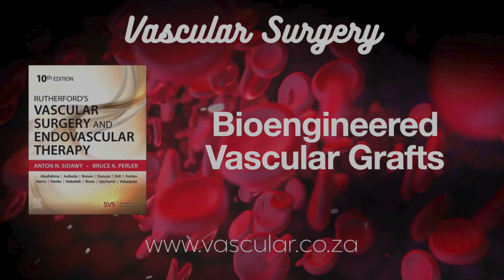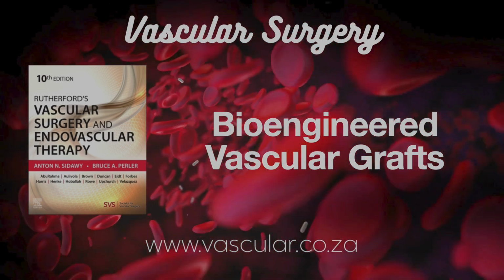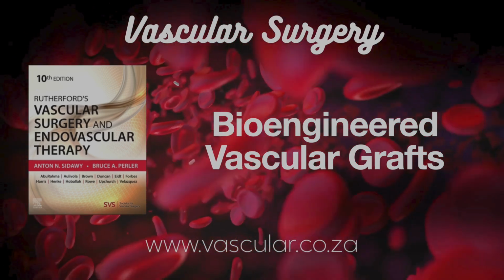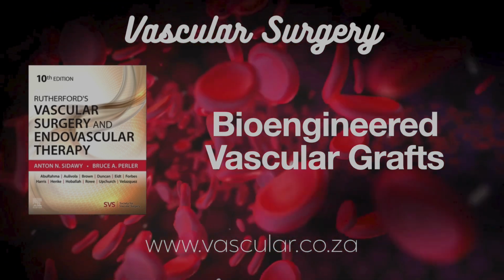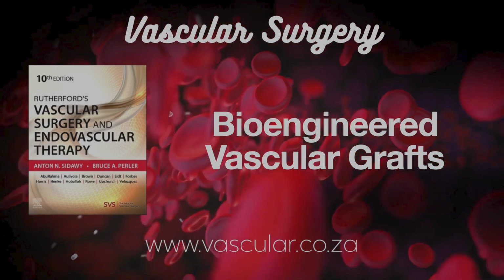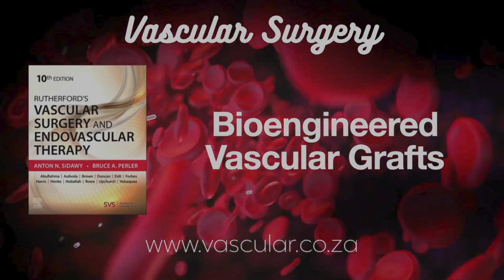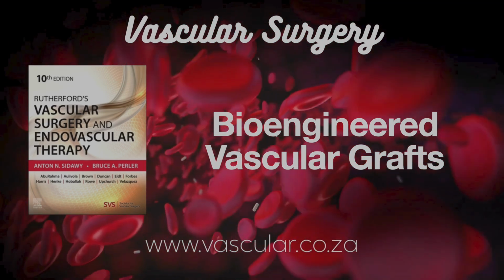Yes. Cytograft commercialized this sheet-based technology, creating the Lifeline graft using the patient's own cells, autologous. It was targeted for hemodialysis access. How did the trials go? Preclinical looked good, but the early phase 1/2 clinical trial, well, it had a pretty high early failure rate. They later figured out it was likely due to using some bovine proteins during the manufacturing, which caused an immune reaction in patients. An unexpected complication. Yeah. They also saw some issues with the grafts dilating or stretching out over time, and again, that super long manufacturing time, 24 weeks, was a major practical barrier. Not exactly off the shelf.